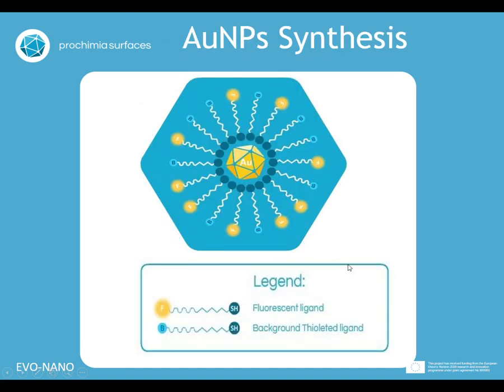And if the gold nanoparticles are introduced into the cell, it's difficult to observe them because they are too small, and frequently a confocal microscope, for instance, is not able to observe them. So it's much better and more convenient if these gold nanoparticles are functionalized with thiols terminated with a fluorescent group, and the preparation of these nanoparticles functionalized with fluorescent dye can be performed in the same way as previously for the introduction of the API.